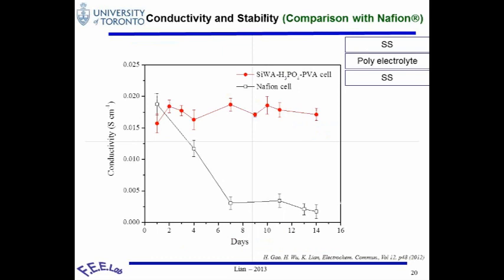So the one that we selected was Nafion. We use the ionomer from Nafion. We compare that with our Gen 2 material in the same way, so that we paint them in the same way, sandwich them, and make the device. Here is the comparison of Nafion ionomer versus the PVA phosphoric acid, SIW phosphoric PVA devices.